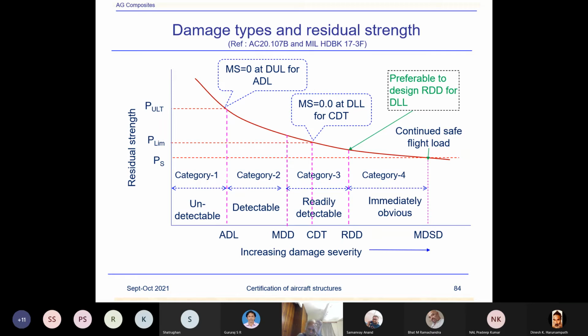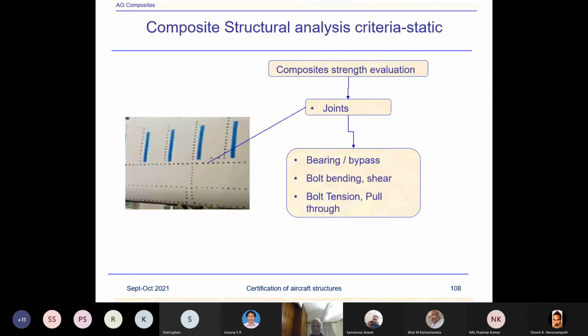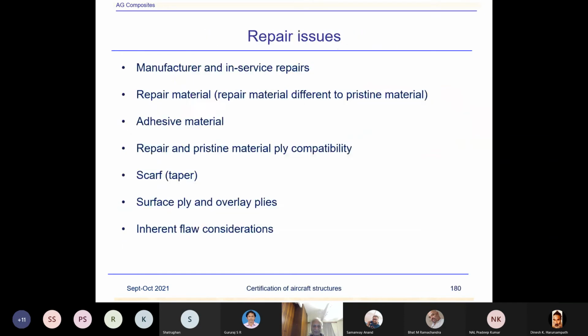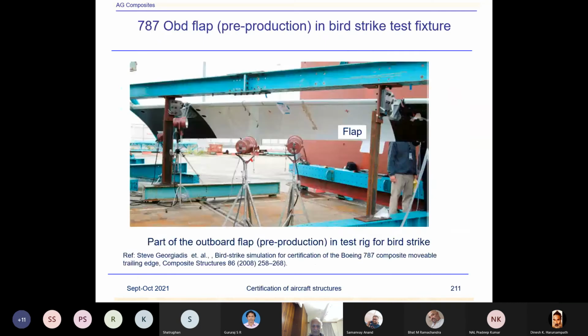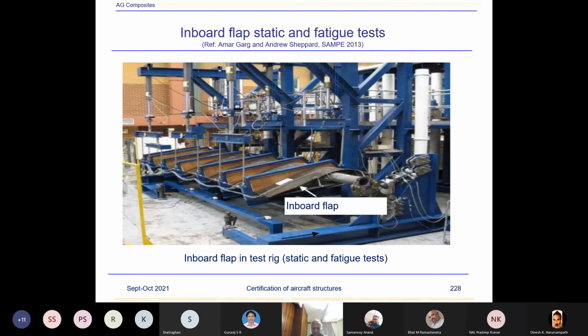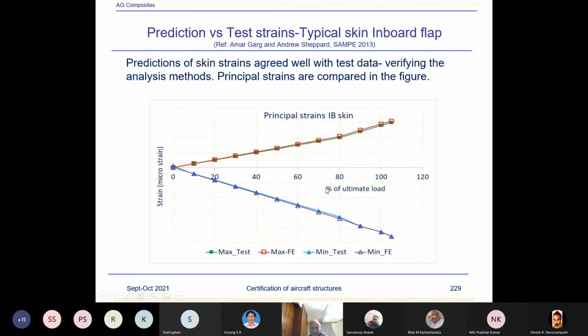Now, what does it mean? When you are certifying these components, you are trying to certify by analysis. And analysis methods are being verified by the test. And as I explained, when you are talking of the verification by test, the component test is done at room temperature, and basically the information you get, say the inboard flap test, was done at room temperature. And when we are trying to verify that the analysis is able to predict the structural behavior, this is what you do. You test in order to simulate the prediction of strains by your FEM method and match it with the test data.